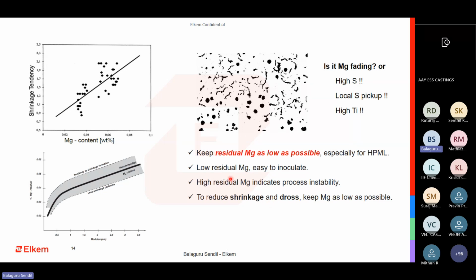When you have low residual Mg, it is very easy to inoculate. If you have high residual Mg, you need more inoculation. It basically indicates your process is unstable. The only correlation we need to take with respect to magnesium is the microstructure.